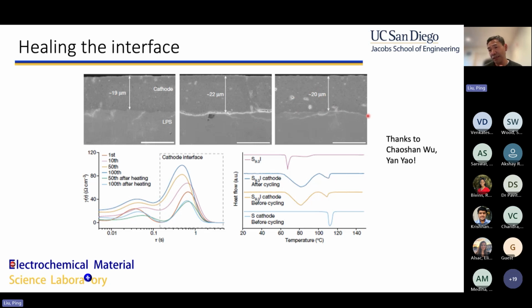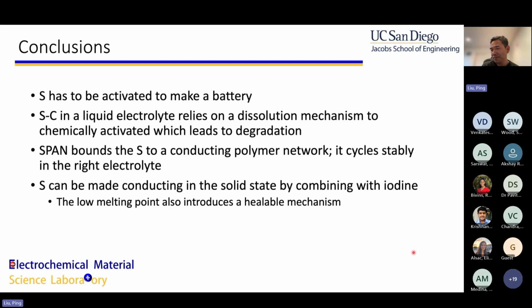This is because we can remelt the material, because the sulfur iodide material has a melting point at 65 degrees C. With this, we can reset the impedance, which is shown on the left, and then we can reset the microstructure. So we continue to work on solid-state lithium-sulfur. There's still a lot of work that remains to be done. So with that, I just want to wrap up.